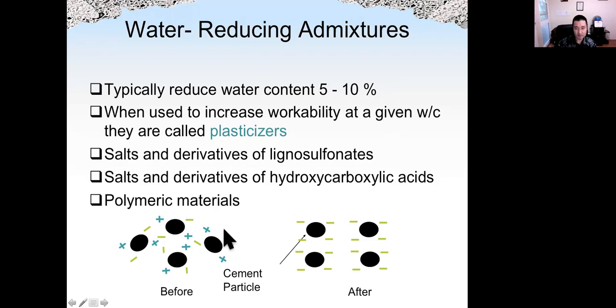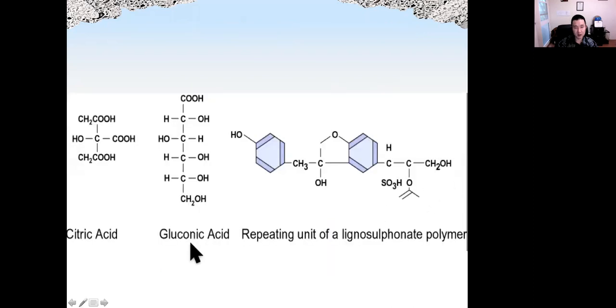How does this water reducing agent work? This shows one of the functions of them. The molecule of the water reducing agent can neutralize the surface charge of cement particles. We can see here, before adding water reducing agent, the surface charge of cement particles could be positive or negative, and positive and negative charges will attract each other. So water reducing agent will neutralize the surface charge, making them all negative charge, so they will repel each other. That's one reason why it can reduce the water requirement. Here are some examples of the molecule structure of water reducing agent. Again, most of them are organic matter.